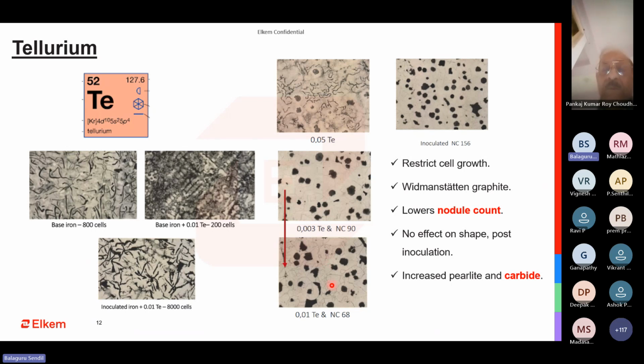It not only increases pearlite, it also increases the potential of carbides. So this is again a dangerous element, tellurium. That is why, when we say it is chill, most of the time you can see carbides. The same can be applicable here. If you etch this properly, you will be able to see a much lower nodule count. When you have a lower nodule count, the tendency for carbides is quite high. So this is what it is going to do to your base metal. Tellurium is much more dangerous than the previous element we discussed. The same condition in there, the nodule count was 156.